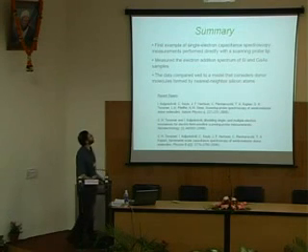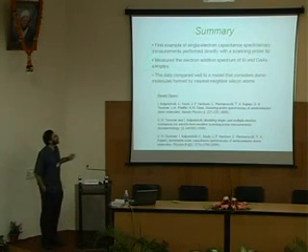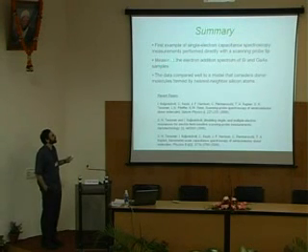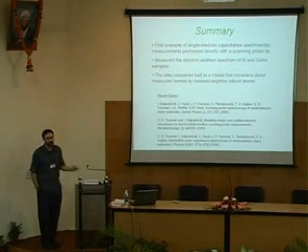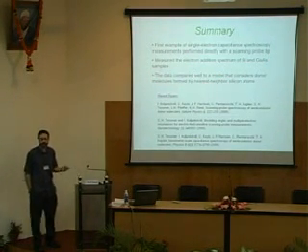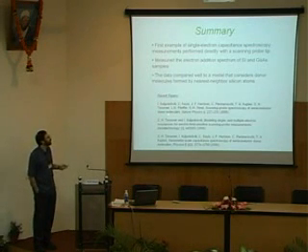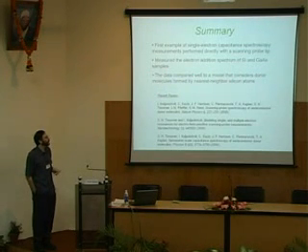So here are my conclusions. I didn't make a really big deal out of this, but these are the first single electron capacitance spectroscopy measurements performed directly with our scanning probe. We use them to look at the addition spectrum of electrons going onto donor atoms and acceptor atoms in silicon and gallium arsenide. For the gallium arsenide work with silicon dopants, the behavior is well explained by considering nearest neighbors as effectively forming donor molecules.